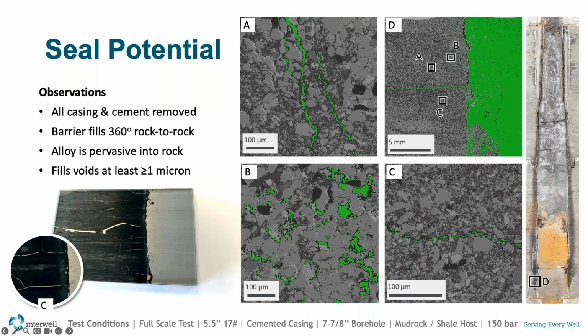In this slide here, the barrier on the right-hand side of the slide was, again, that image you saw earlier, cut open 180 degrees. From that full-scale test sample, a section of that highlighted in the box D was taken. Then from that sample D, we picked 3 other areas located A, B, and C to take an understanding of how this product actually permeates and gets into the caprock, if in fact it does do that.